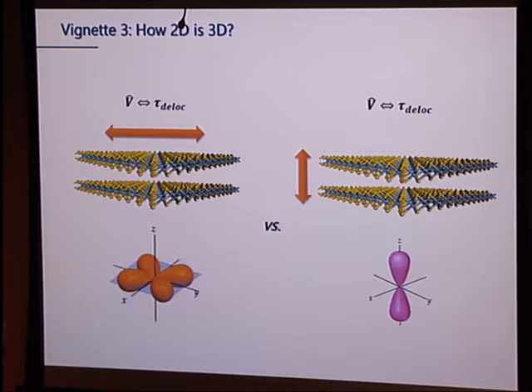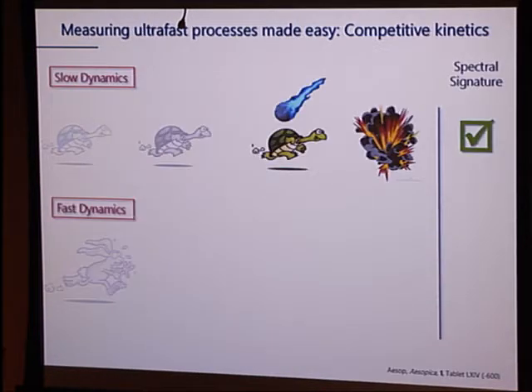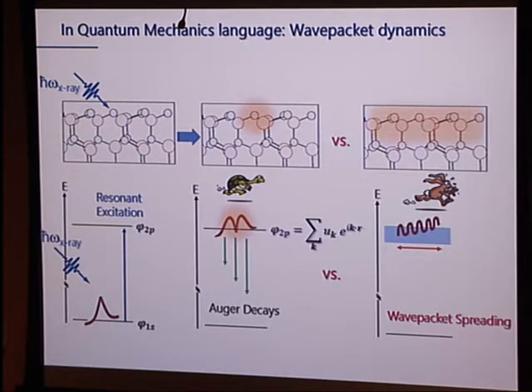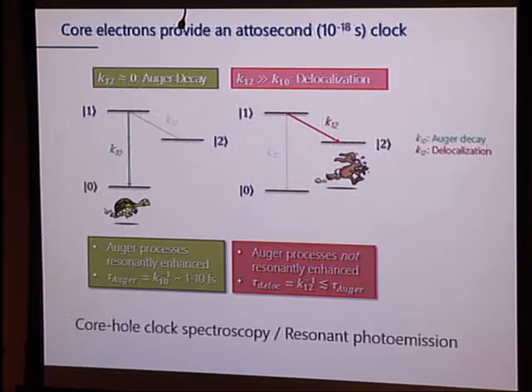Let me not go into details here, and I'm going to skip this. We use X-ray spectroscopy to do this. This is resonant X-ray spectroscopy that we call core hole clock spectroscopy, where the idea is very simple. We have a clock that we know, that's the Auger decay of core excited electrons or molecules or surfaces, and we can beat against that any other process, which might, for example, be carrier transport. Since that decay is, A, well known, and B, very fast, on the order of 1 to 10 femtoseconds, this allows us to access very short timescales that way.